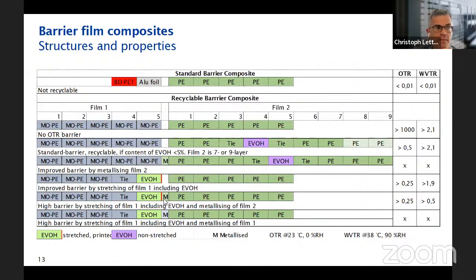And now I can again start playing with metallizing technologies or AlOx and SiOx technologies to improve these barrier properties even further in the next step. So you might wonder and say, okay, this guy is talking about a monomaterial solution and EVOH is now coming into the game. Why is this still considered a monomaterial solution? Well, common understanding in the market is that if you reduce the EVOH well below 5%, it is regarded as being recyclable. That's the important thing, that in the total combination, in the pouch itself, the EVOH content is below 5%. So that's the target, either in the sealant layer or in the stretch layer.